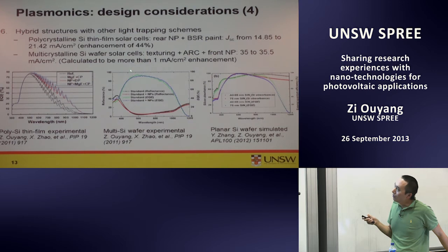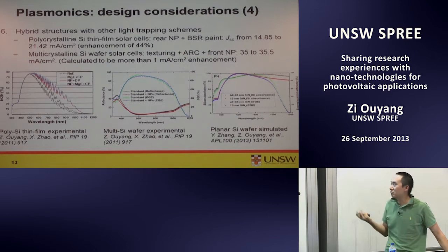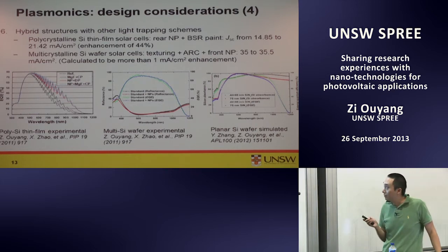transmittance. So somehow, as you can expect, the scattering breaks the ring, and probably the path length changes, so you won't have the ideal cancellation anti-reflection effect. But at the short and the long wavelengths, you really get benefit from the nanoparticles. So you have a little bit of trade-off, but you boost on the short and long wavelengths. For this particular solar cell, we have not much, but good enhancement from 35 to 35.5 milliamps per square centimeter. And this result actually matched very well with one of our earlier publications where we simulated the result, which also showed the same decrease at the medium wavelengths and boost at the short and long. So this experiment was confirmed by the theory, or the other way around.